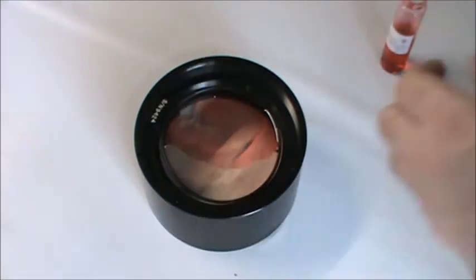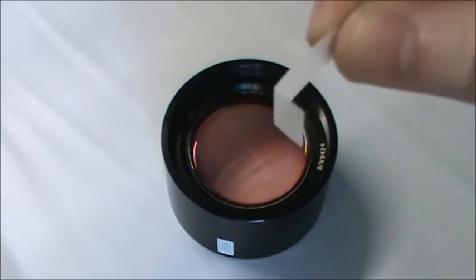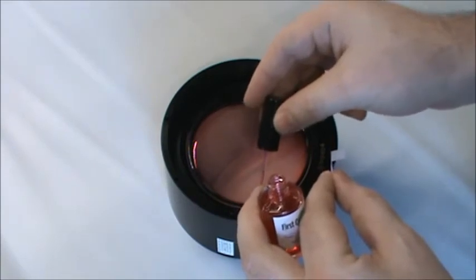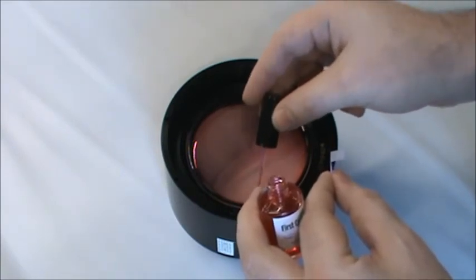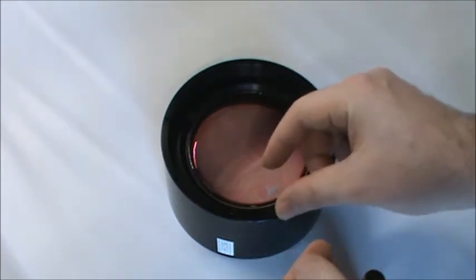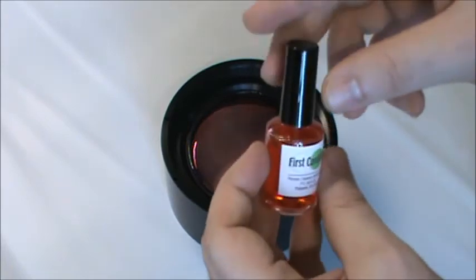Allow the polymer to start drying for about 2 minutes. Afterwards, we will take our chemically inert mesh strip and embed it into the polymer. To do so, take a 15ml vial and brush and lightly re-wet a section of the polymer near the edge. Bend the mesh strip into about a 90 degree angle and place it on top of this section.